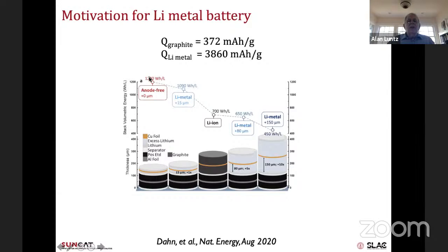So what most people have tried to do is to develop what's called an anode-free battery. You just have a slightly bigger cathode, and so you store a little bit more lithium in the cathode when you start, and then you first charge the battery and plate out the lithium. And then you can go back and forth between discharge and charge using up all of the lithium. And then you get a huge increase in volumetric energy density. So this is the game people are mostly playing.